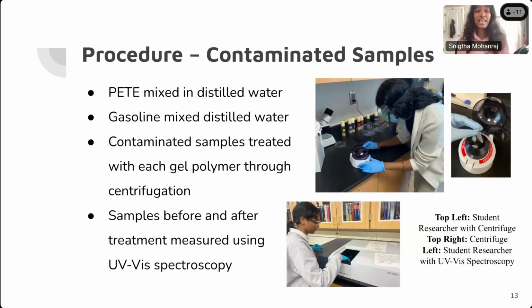So then I prepared the contaminated samples by mixing PETE and gasoline into distilled water, and these contaminated samples were treated with the gel polymers through centrifugation, and the samples before and after treatment were placed into the UV-vis spectroscopy in order to collect data.